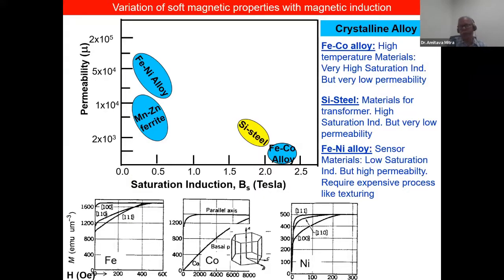If you consider crystalline alloys, there are three categories of crystalline magnetic materials obtained from the application point of view: iron-nickel alloys, silicon steel, and iron-cobalt alloys. I have plotted it between the saturation induction and the permeability. For the application point of view, we always try to get the material which has high saturation induction and high permeability. But if you see these crystalline alloys, iron-cobalt has very high saturation induction, but its permeability is also very low.